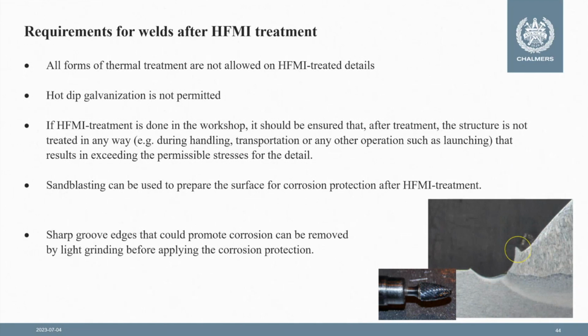Sometimes HFMI treatment results in sharp grooves, like shown in the photo here. These might be threatening from the point of view of corrosion protection. Now you see the circle or the curve that you see, the depth of the groove here is around 0.2 millimeters. So these are very, very small. Still, they should be removed by light grinding in order to ensure that we get a good coverage of the corrosion protection afterwards. In many cases, sandblasting would be enough to remove them.